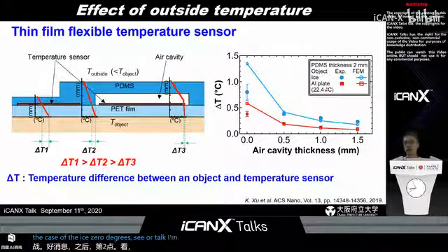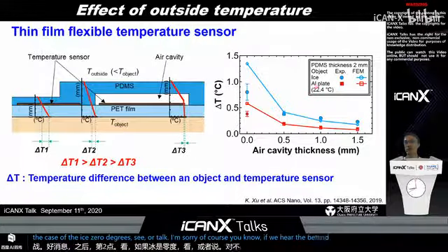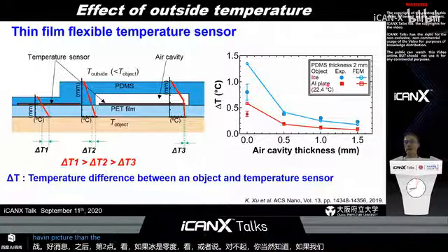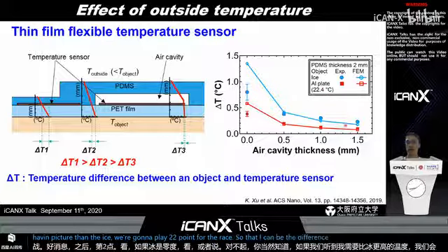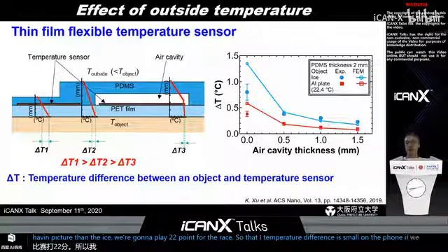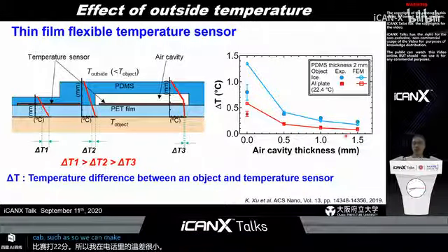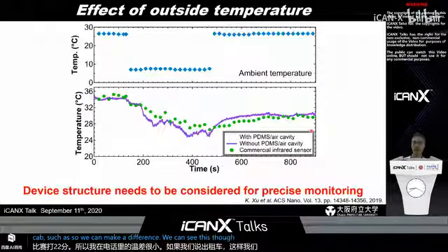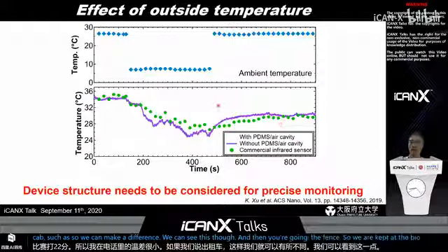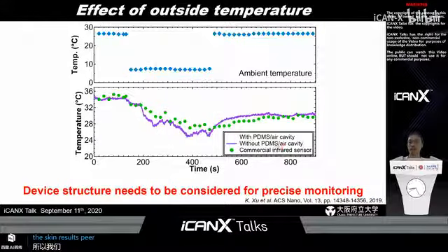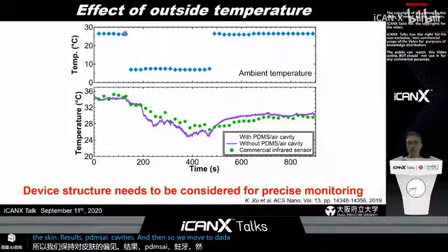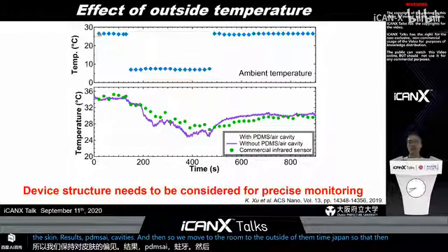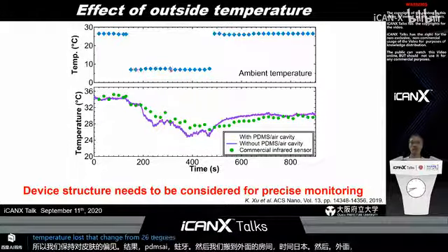And also, of course, if we use a little bit higher temperature than the ice, here we use the aluminum plate, 22.4 degrees C, the temperature difference is smaller. And also, if we use this air cavity structure, we can reduce the temperature difference, as you can see in this result. And then using the sensor, we attach the device onto the skin with and without the PDMS air cavities. And then we move from the room to the outside in the winter in Japan. So the outside temperature is drastically changed from 26 degrees C to roughly 6 degrees C.